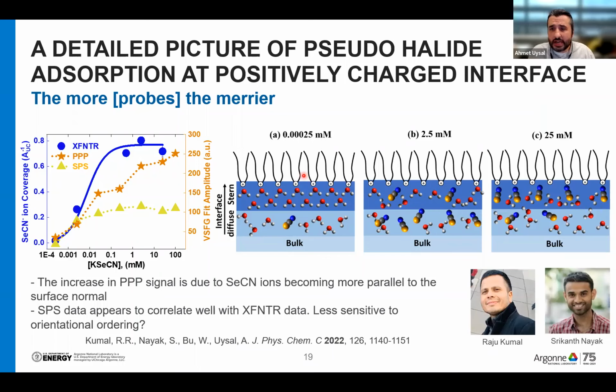And we also have reflectivity data and GID data on these systems. By combining all of that information, here is what we think. At very low concentrations, we believe most of the ions are adsorbed in a way that they are not directly interacting with the surfactants. When they are not directly interacting with the surfactants, their orientational ordering is a little more distributed. That is why the PPP signal is not that strong at that concentration. The total number is not changing from 2.5 to 25 millimolar, but we think more ions are moving from the diffuse layer into the Stern layer, and they get more parallel to the surface normal between these two concentrations. That's why the fluorescence is pretty flat, but the PPP signal keeps increasing.